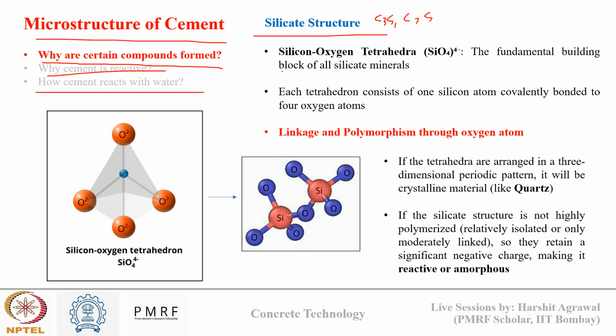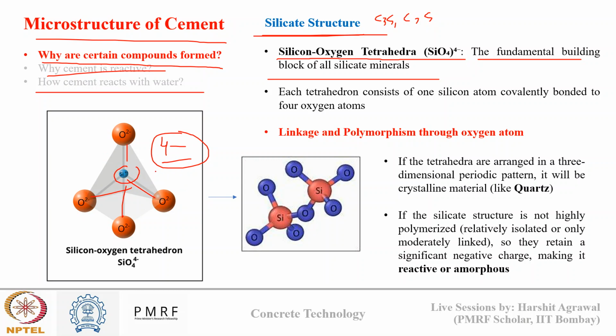When we talk about silicate structure, silica is in the form of silica-oxygen tetrahedra, SiO4 4-. This is the fundamental building block for all silicate minerals. Each tetrahedron has one silicon atom, which is covalently bonded to four oxygen atoms, and it has a net charge of -4. So in this tetrahedral structure, there are four unbalanced charges present. The presence of these unbalanced negative charges on the oxygen atoms gives silica the ability to show linkage and polymerization through oxygen bonds.